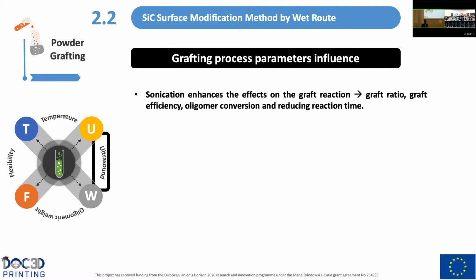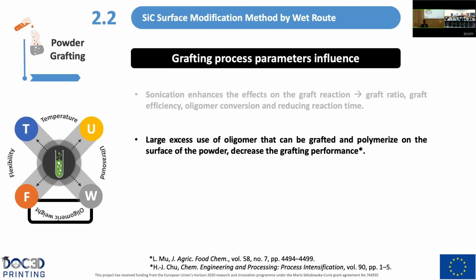Moreover, we optimized more parameters. For example, regarding the ultrasound, we saw that sonication enhanced the grafting by increasing the graft ratio, the graft efficiency, the oligomer conversion, and the reduction of reaction time. Next, we studied that a large excess of oligomer that can be grafted and polymerized on the surface of the powder decreases the grafting performance, as reported in literature.